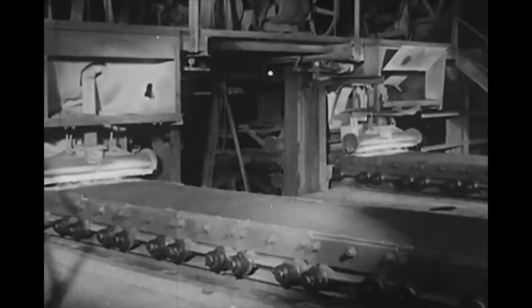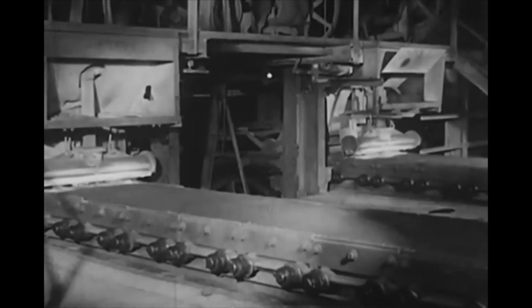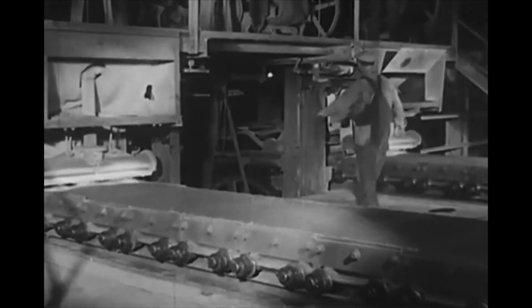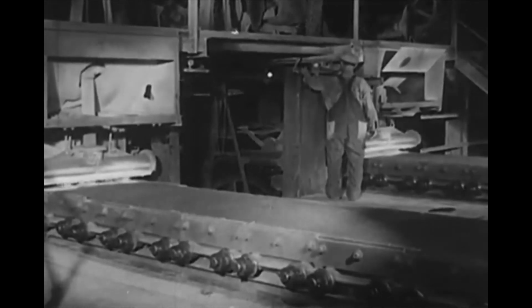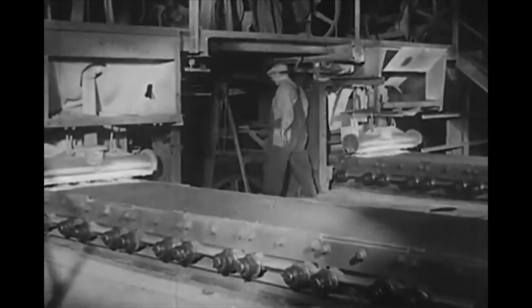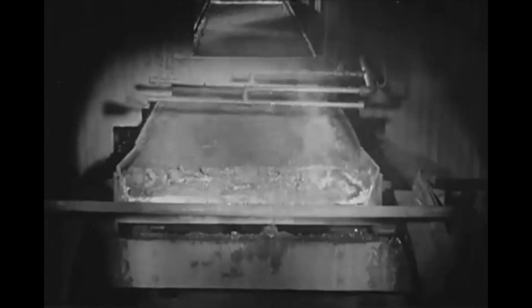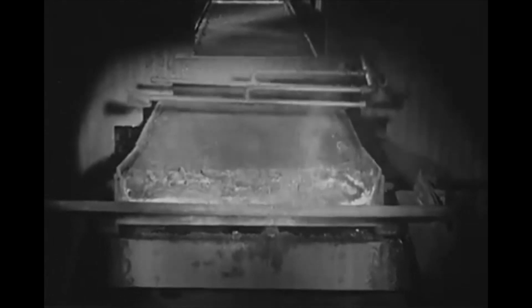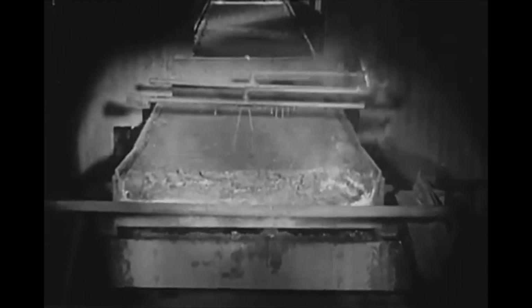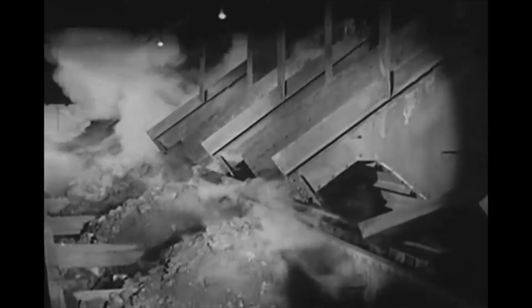Similarly, the gas burners ignite the sulfur in the mix. The suction of the fans draws smoke and fumes down through the sinter bed. The fumes are collected and treated for the recovery of lead content. Burning for 10 to 15 minutes reduces the sulfur content and leaves the pellet in the form of a porous cake or clinker, which is cooled by a water spray.